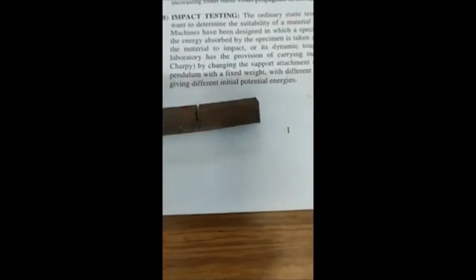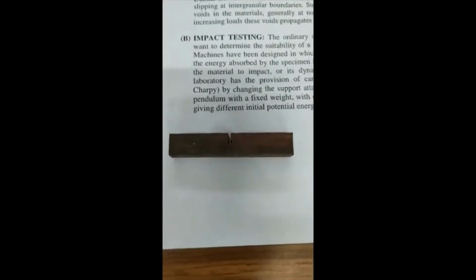For fixing the specimen, you need to go to the bottommost position of the setup. So this is your specimen. You can see some rust, because the specimens were kept since last year. In this specimen there is one notch in the center. This is called a U-shaped notch. In Charpy and Izod impact tests, there will be a notch on the specimen.